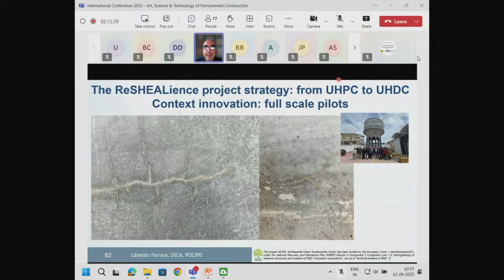So actually, because the material has this self-healing capacity, the cracks can form, but the cracks heal, and there is no significant degradation of the material performance. We observed this in the lab up to 1 year, and we are observing this in the field. All these pilot structures, I have to say, they are in operation for about 4.5 years, because they were all built in the late 2020, early 2021. So it's now about 5 years, and it's a very unique opportunity to really monitor them in the real conditions. And as a matter of fact, this is the advantage of UHPC, of ferrocement, because of the very tiny distributed cracks, you do not have significant degradation.